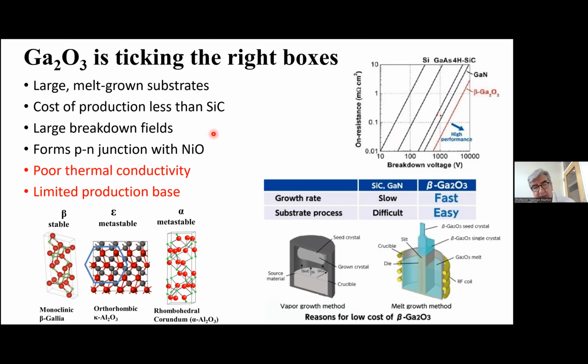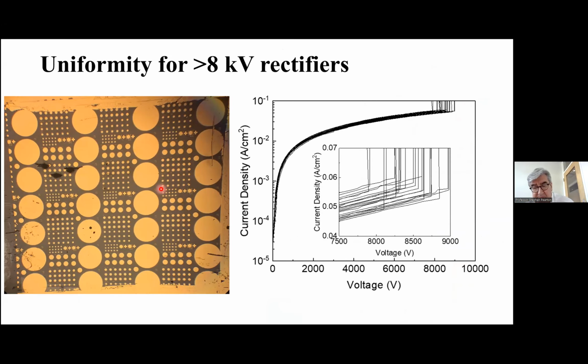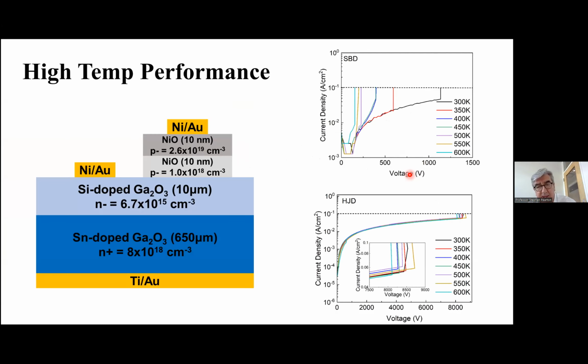So gallium oxide has large area substrates, large breakdown fields, low cost of production. It doesn't have p-type doping, but it forms a p-n junction with nickel oxide, which is a p-type oxide readily deposited by a number of different techniques. It has low thermal conductivity, but that's really an engineering issue. You can use the same kinds of tricks that have been used with gallium nitride, diamond heat sinks and so on, or both side heat removal to try to address that. So you can buy vertical rectifier epi structures from Novel Crystal Technology in Japan. And if we just make devices over 1 centimeter by 1 centimeter area, we readily get breakdown voltages of 8 or 9 kilovolts with simple device structures. And as I said, you can make a p-n junction.